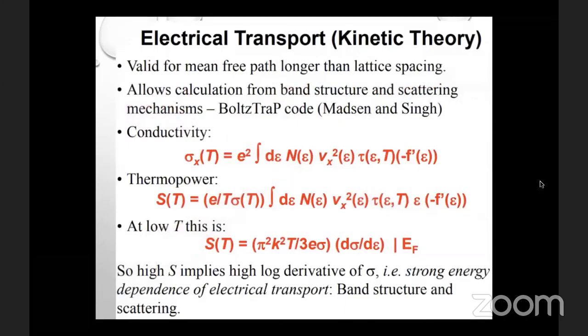The BoltzTraP program uses electronic transport theory. This theory is valid for mean free paths longer than the lattice spacing, and allows calculation from band structure and scattering mechanism using the BoltzTraP code. Here you can see the conductivity and Seebeck coefficient formulas.